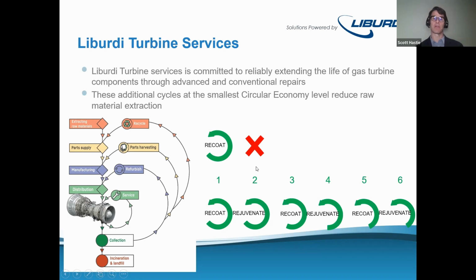on the second repair, they're going to get rejected. And that's not all components, but it's just an example. And so what Liburdi's done with some of these components is we'll do a recoat repair, just similar to other repair vendors, but we'll also really look at the future of the component, making sure that it's adequately coated, so that there's no degradation of the external features, make sure we're not removing unnecessarily any of the wall thickness of the component, and then the next time through, we'll rejuvenate. We'll get onto that a little more.